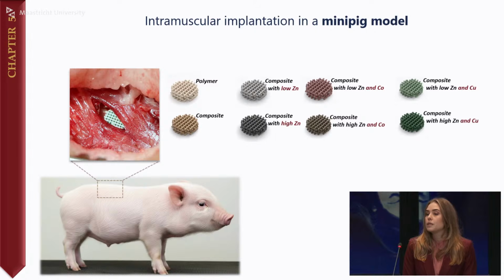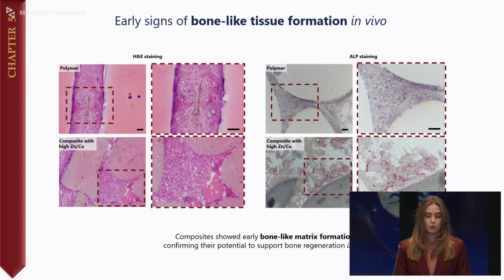After obtaining these promising results in the lab, it was time to investigate the biological properties of our scaffolds in a living organism. And for this reason, we implanted all of our scaffolds in the muscle of a mini pig. After 12 weeks of implantation, we observed that all scaffold formulations allowed ingrowth of connective tissue into their porous structures. In the case of composites containing zinc and copper, we saw an increased formation of matrix.